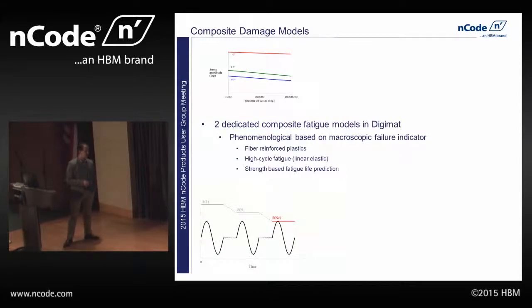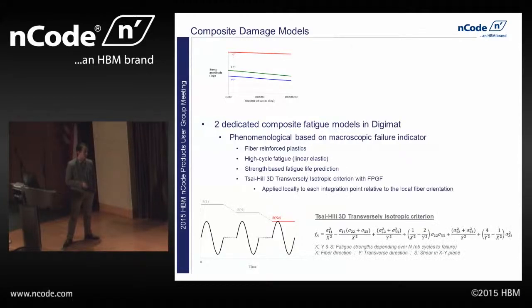So this model is really aimed at tackling high cycle fatigue. We mentioned before that these materials are highly nonlinear, but in this case, we're only going to be looking at the linear properties. And this is a strength-based fatigue life prediction. So instead of actually accumulating damage in the material, we're going to reduce the strength of the material for each individual cycle that this material is seeing, which is, I think, not so dissimilar from most of the methods we've been talking about today. In order to determine that strength of the material, though, we're going to use what is considered to be a relatively unique approach to the Digimat world.